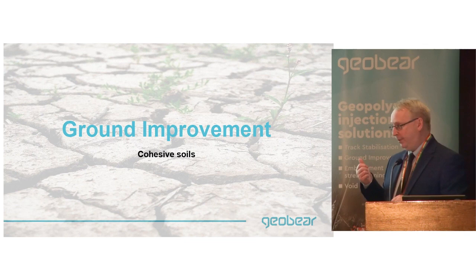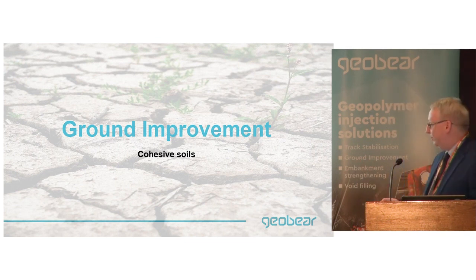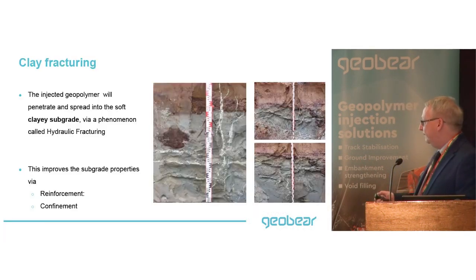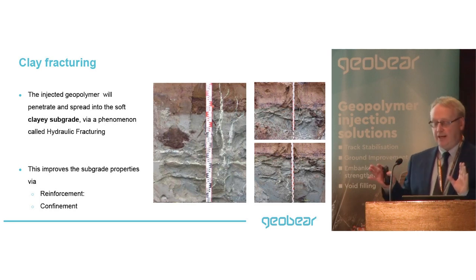That's shown in this picture. These are the vertical and horizontal fractures of geopolymer within a clay matrix, typically forming a cross pattern of interlocking fractures. Consider a very soft clay, maybe 10 to 15 kPa, and inside it you put a geopolymer that could be 1,000 kPa in compressive strength. It's rather like putting steel into concrete, reinforcing the soil.